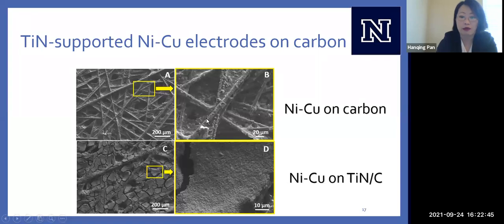We had these carbon paper spindle fibers, and the little tiny balls and clusters on top of that is our copper nickel. When we put down a bed of titanium nitride, this picture right here reminds me of, you know how when you have mud and then it dries and it cracks? That's what it reminds me of. But the titanium nitride, when it's added, it's helping the nickel and copper deposit so much more uniformly. So now it's no longer depositing only along the spindles, but it's depositing almost everywhere. And so when you zoom in, this looks like a very meshy, spongy material, and it's just so much fun to look at.